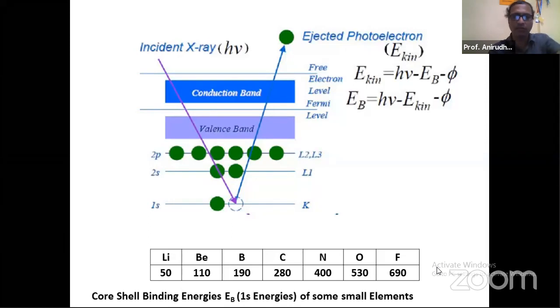So the point to be noted from this slide is that the core shell binding energies of elements are distinctly different. They are clearly, well separated, which helps you identify different elements on surfaces if you examine their core shell electron energies. Say for example, if I am getting a value close to 110 and I am suspecting beryllium, then I can say that yes, beryllium is definitely present in the system. So this schematic explains what this photoelectron is, what its kinetic energy is, what its binding energy is, and how we can identify different elements from information related to core shell binding energies of elements.